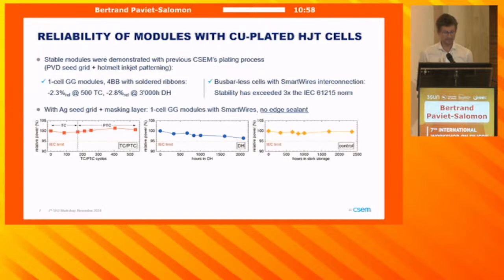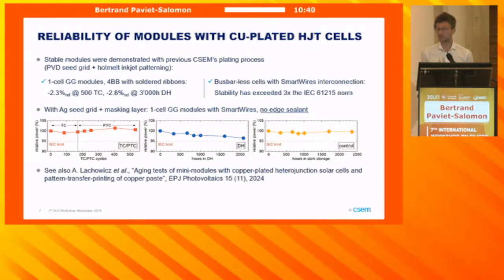More recently, with the process I'm presenting today, we reached full stability for TC and PTC for glass-glass modules with smart wire and with no edge sealant, with stability up to 2,000 hours of damp heat, which for such a module scheme is quite remarkable. And eventually, if you want a bit more detail, I encourage you to read this recent paper by my colleague Agatha Lachowicz, in which she is summarizing recent results of stability for plated devices in modules.